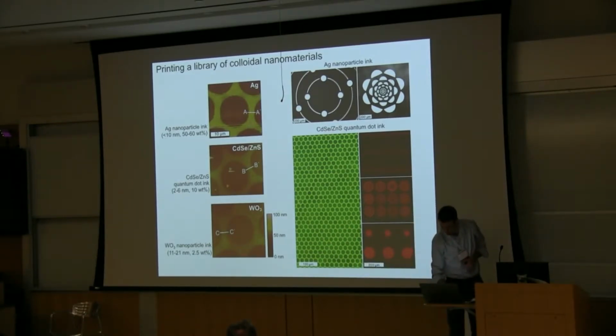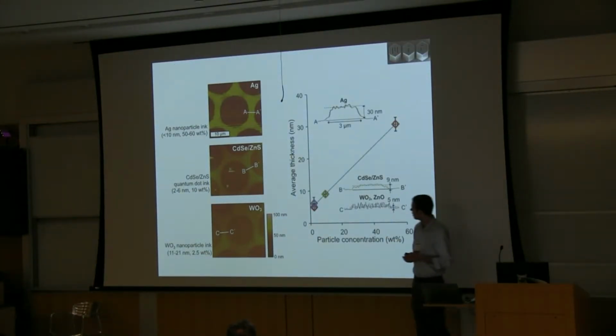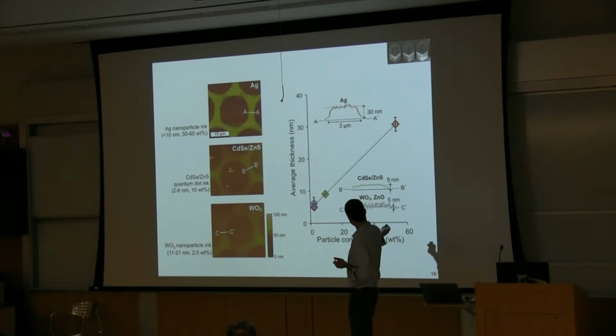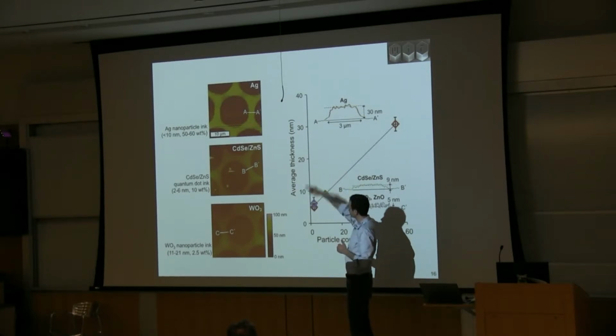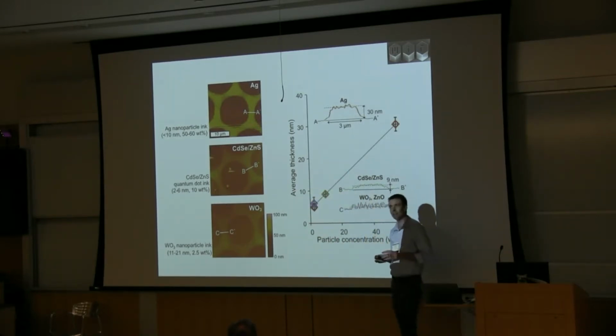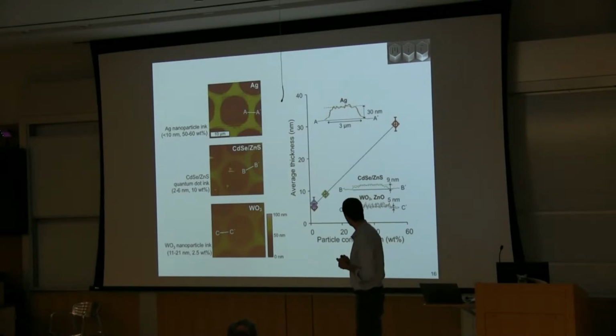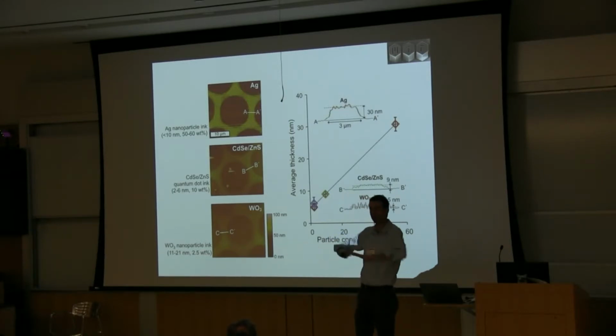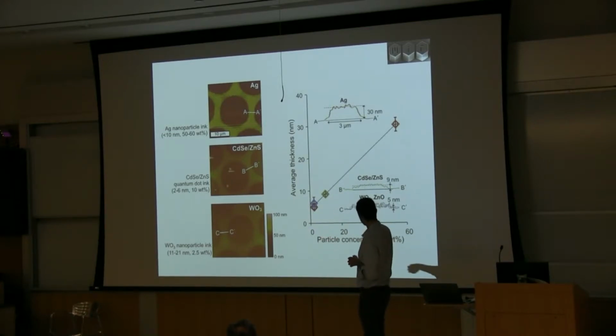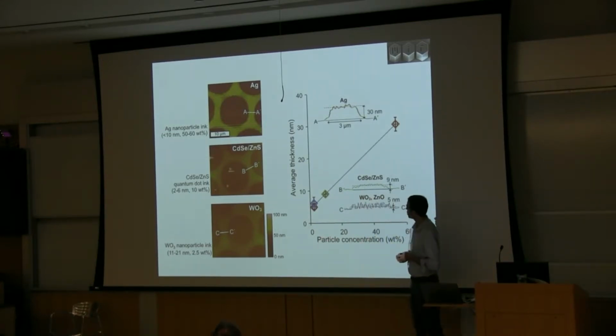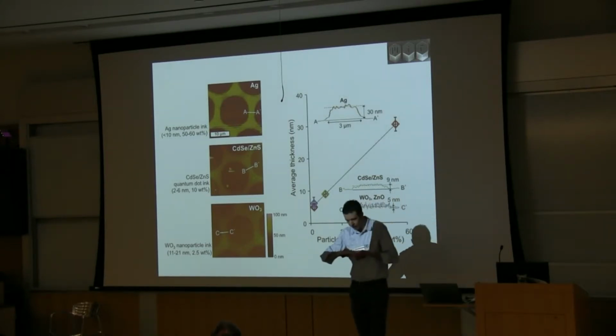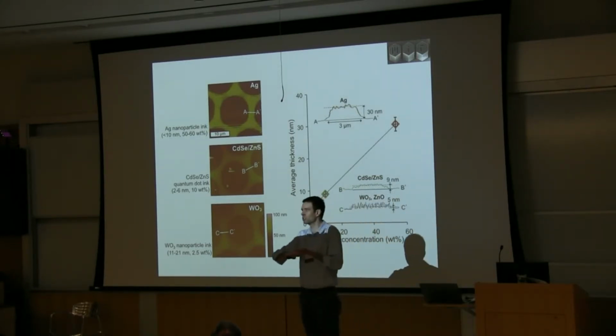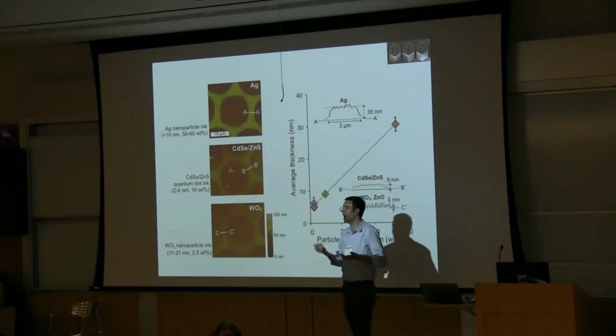And one interesting thing we found by comparing all these different materials is that the thickness of the layer that we print is pretty proportional to the concentration of particles we have in the ink. So by comparing all these different types of nanoparticles, with slightly different sizes and different material chemistries, we find that after the ink layer dries, when we use the same stamp pattern and same stamp preparation, we end up with a thickness of solid that is proportional to the starting particle concentration. And that's interesting to us in hinting that the mechanics of transfer are leaving the same volume of ink behind every time.